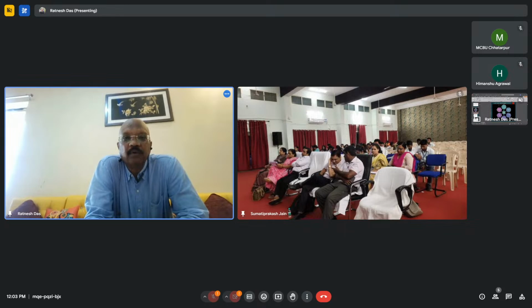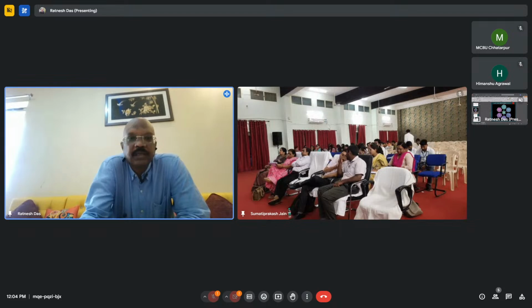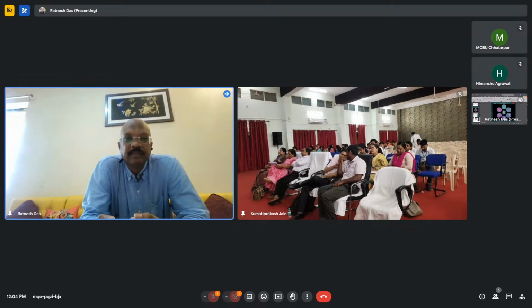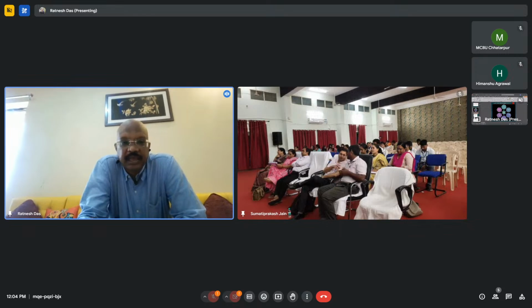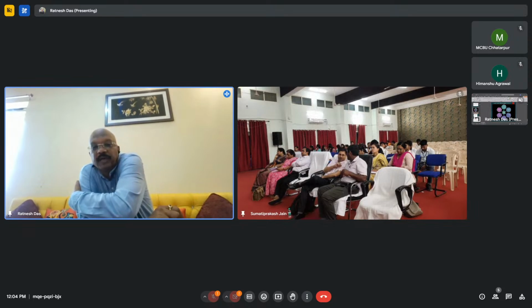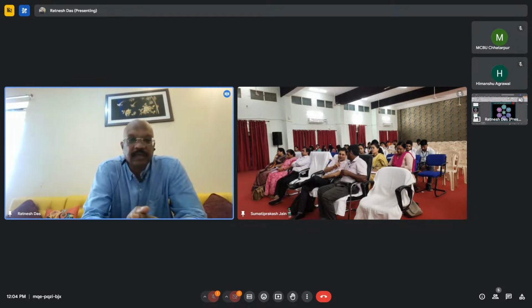The X-ray diffraction of multi-walled carbon nanotube, functionalized multi-walled carbon nanotubes, and silver nanoparticles all were done. The deposition of silver nanoparticle on the multi-walled carbon nanotubes was done. The same image of multi-walled carbon nanotubes with carbon paste electrode is shown. Here you can see this is the XRD, and three graphs are there. First is your multi-walled carbon nanotube. Second is multi-walled carbon nanotubes coupled with silver nanoparticles, and third is silver nanoparticle, multi-walled carbon nanotubes, and copper nanoparticles.